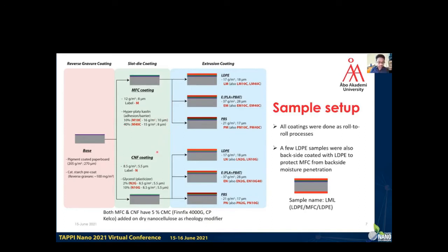And then coming to CNF coatings, we had the pure CNF coating at about 5.5 micrometers. And then we also wanted to see the influence of plasticizer on the barrier properties. So we used glycerol here at 2 and 10% addition levels, labeled as 2G and 10G, at similar thicknesses. And both the nanocelluloses have 5% CMC added as a rheology modifier.